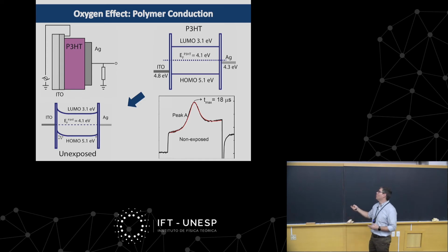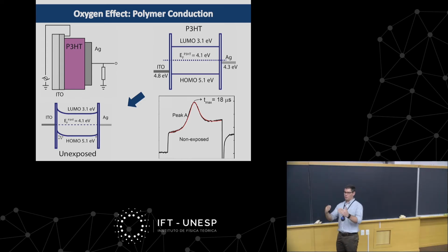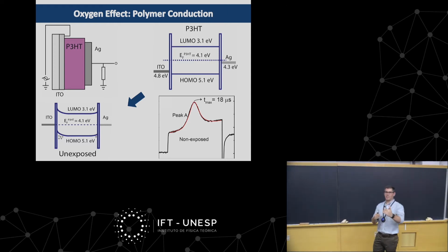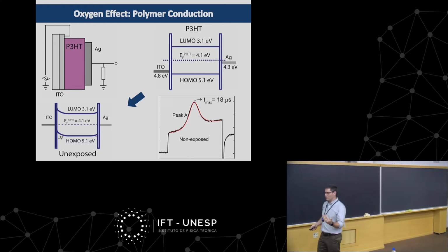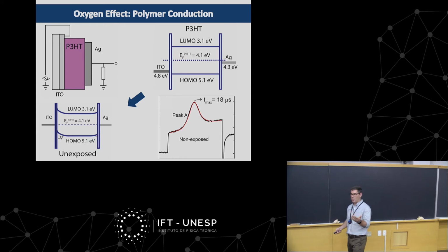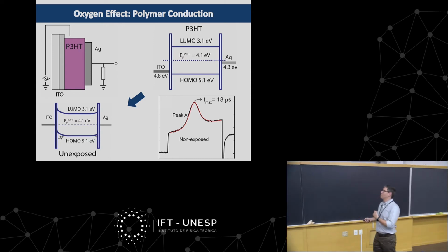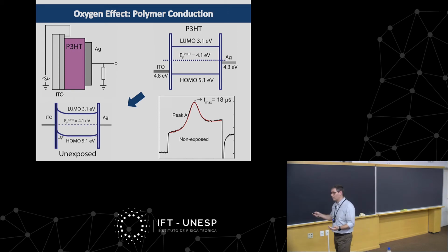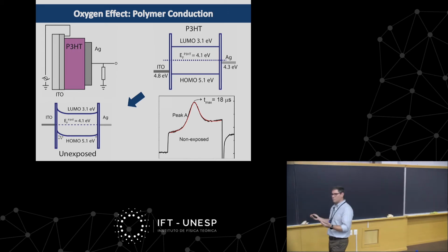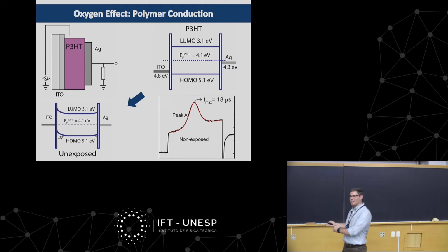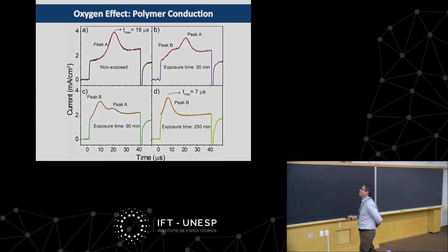And because when you remove those charges, you basically take a system that is in equilibrium and take it out of equilibrium, the system of course wants to restore equilibrium as fast as possible. So you have to use a fast transient response method to really access those charges. And one of the papers we put out based on this work was proposing a technique, a way of accessing that charge and studying that charge.